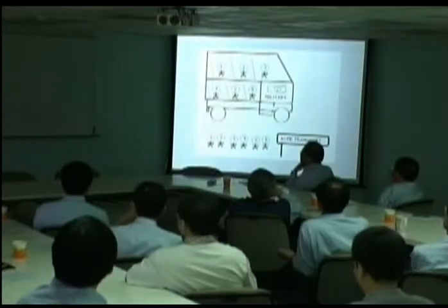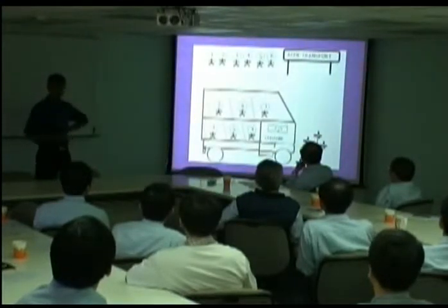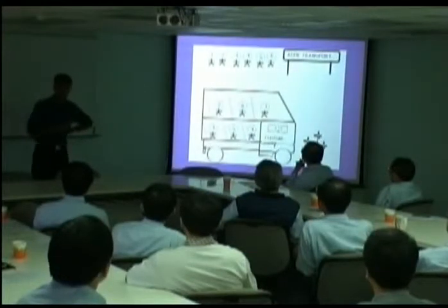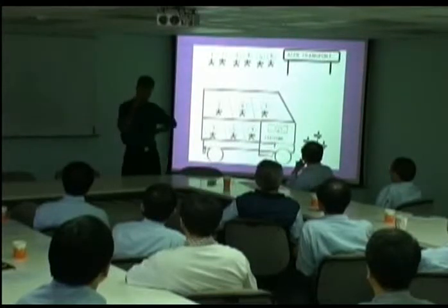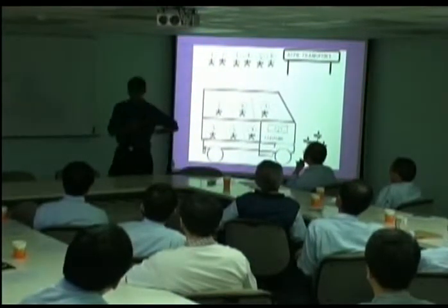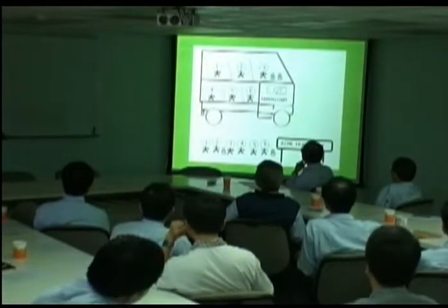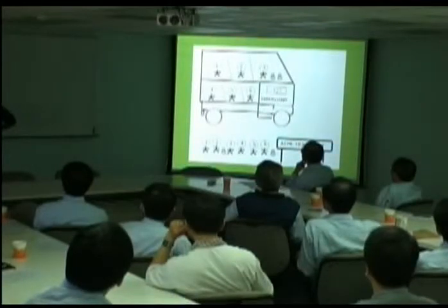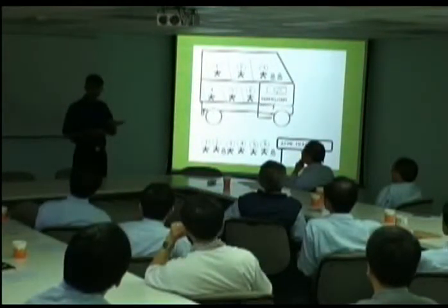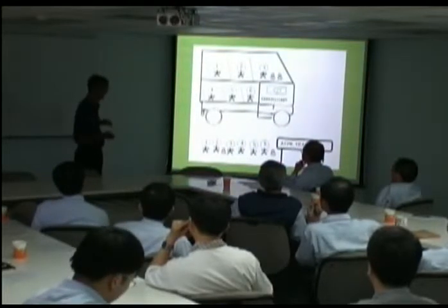Now, by contrast, things like pearlite or allotriomorphic ferrite, you have a queue of civilians here. When the bus arrives, they just rush on board and they sit next to their friends, so strain energy is minimized, and we've lost atomic correspondence. But there is a third kind of transformation. So we had military, we had civilian. You also have paramilitary, where the amount of discipline is between that of the military and civilians. And that is here. You see, we have these small atoms, which don't behave themselves. They go wherever they like. This is the carbon atoms. So it is possible for the crystal structure to be changed, like in martensite, but at the same time, for carbon to diffuse, because carbon is in interstitial position. So this is what we call paramilitary transformation.